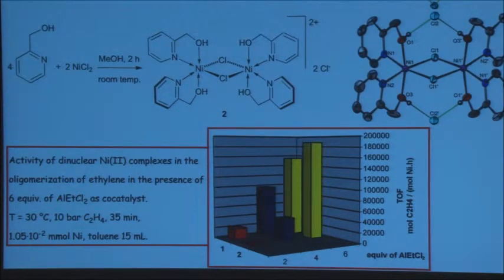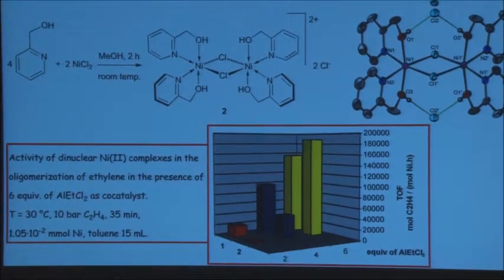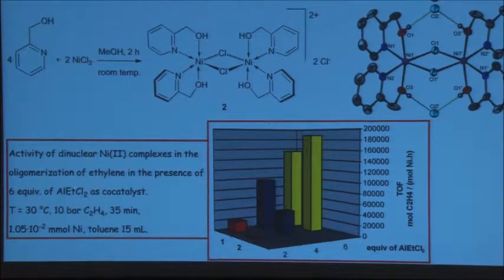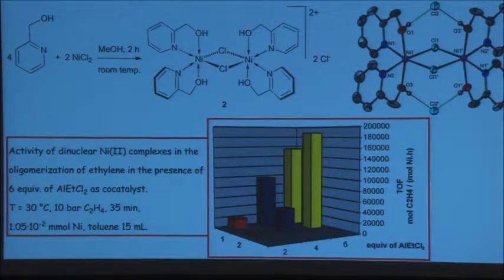To try to be reproducible first and to be able to compare data, the metal loading is always 1×10⁻² millimoles of nickel in toluene. In this catalysis we need to use a co-catalyst, which is chlorethyl aluminum. The function of this co-catalyst is twofold.